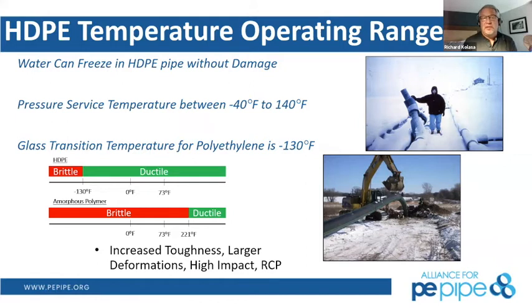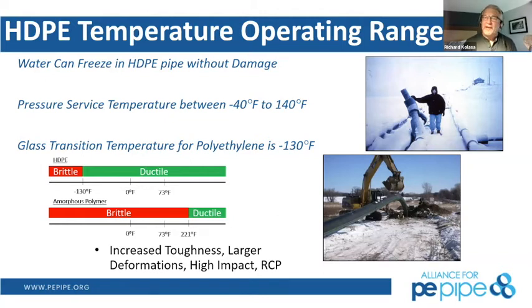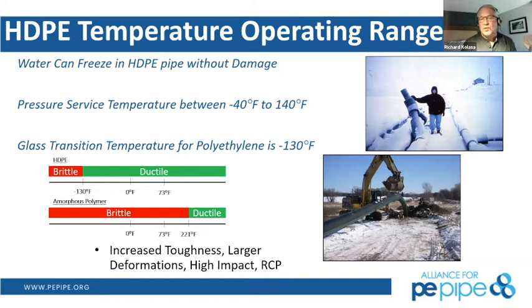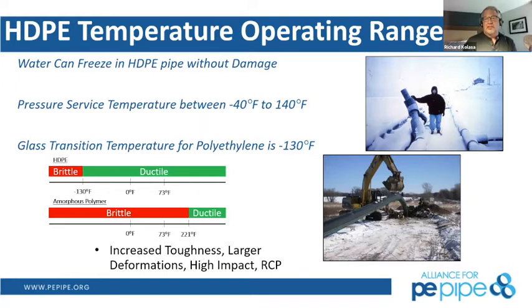For above-ground installation, the pipe can operate in winter but you must understand the effects. A lot of water systems utilize DR 11 pipe, which has a 200 PSI operating pressure — conservative over the typical operating pressures of around 55 to 70 PSI. If that pipe is installed above ground and operated in a warmer environment, it does need to be de-rated according to a temperature multiplier graph, but we still maintain a significant factor of safety covering the pipeline even in hot Phoenix sun.